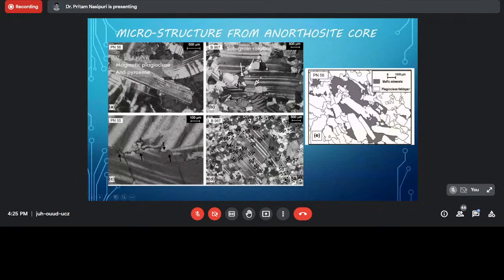Again, subgrain rotation is common where grain-to-grain contact is achieved. This is a microphotograph of the same. This is strain-induced grain boundary migration. You can see a very small bulge, a strain-induced grain boundary migration. Again, strain-induced grain boundary migration yields the grain-to-grain structure, which is the lowest temperature deformation mechanism of feldspar.